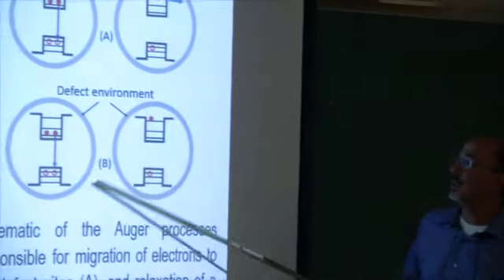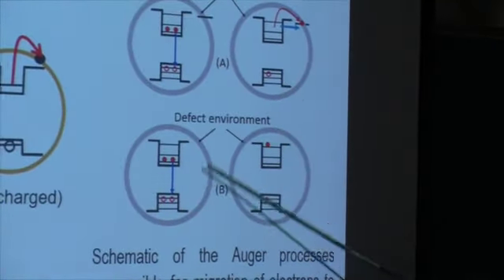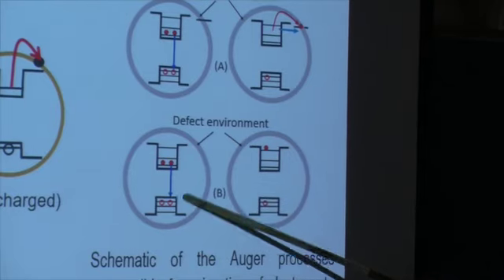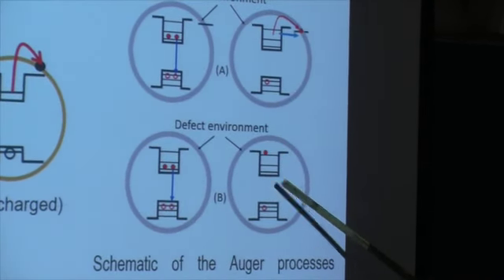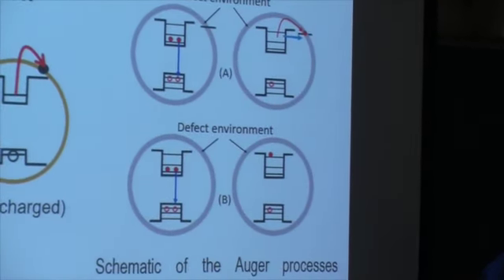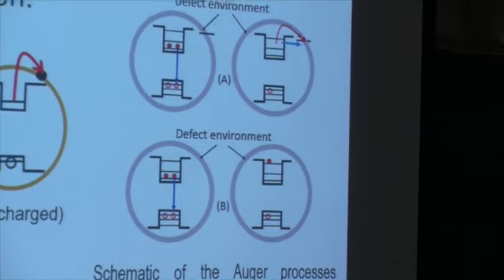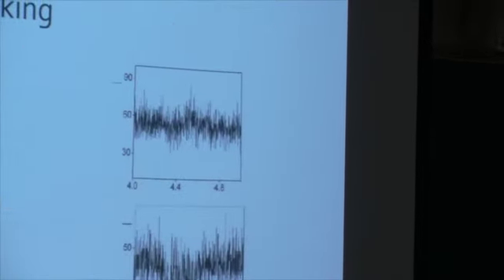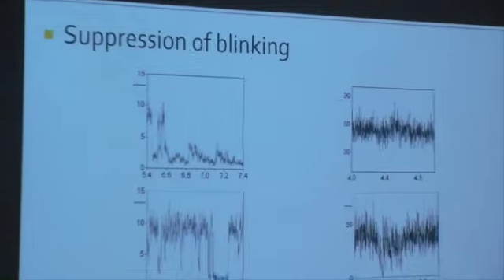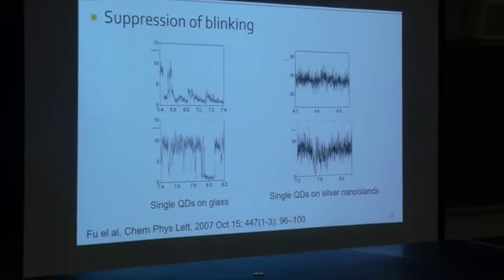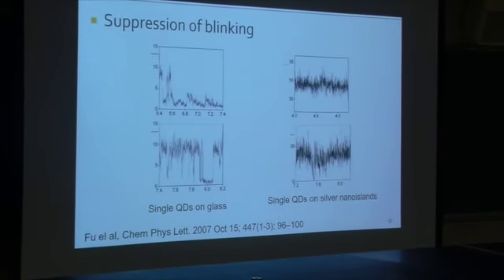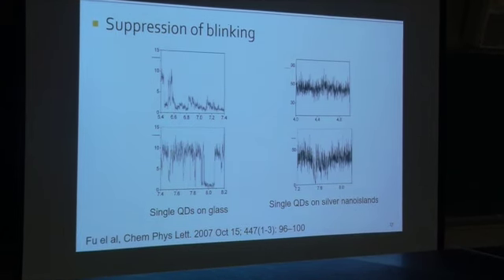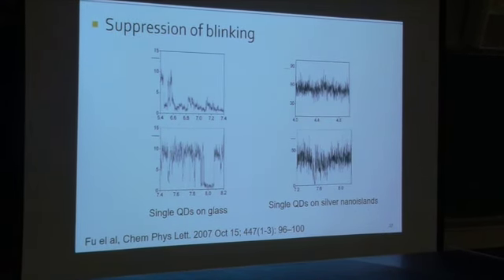You can have multi-exciton recombination, but that process reduces to one. You see that? One goes up and one carrier is left, and it is good for you to get single photon emission. You suppress multi-exciton emission. So this is the work of others, and you can see that you can suppress it if you put silver